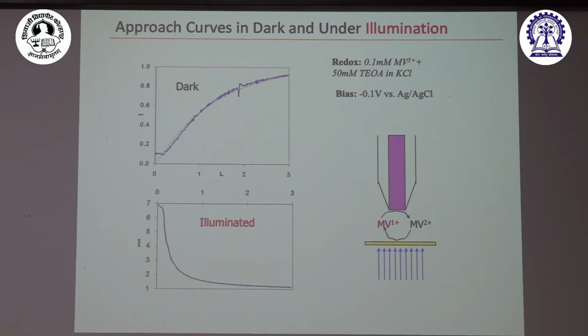Here is the experiment. In the dark there is no charge pair, no electron, no methyl viologen reduction. Okay, and you get negative feedback, like an insulator. But when I expose this to the light, under illumination, it starts showing positive feedback. And now I can measure the effective rate constants here.